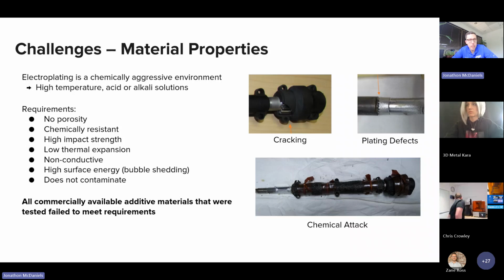needs to have low thermal expansion, so that when you design a part and you need the plated part to come out with a certain dimensional tolerance, when you put it in the hot liquid of the plating bath, that material can't expand and then mess up the plating. You need to be non-conductive.